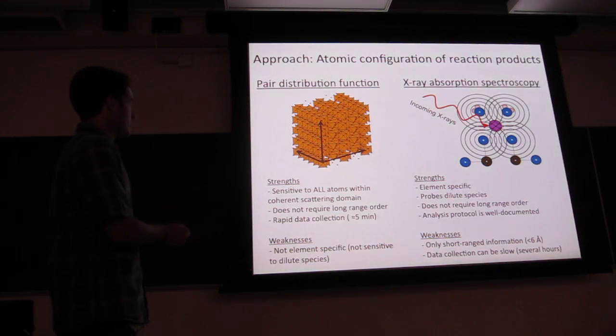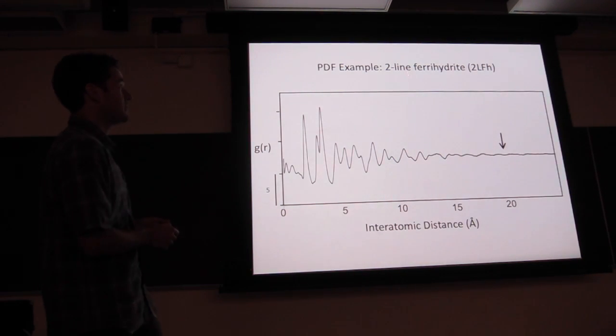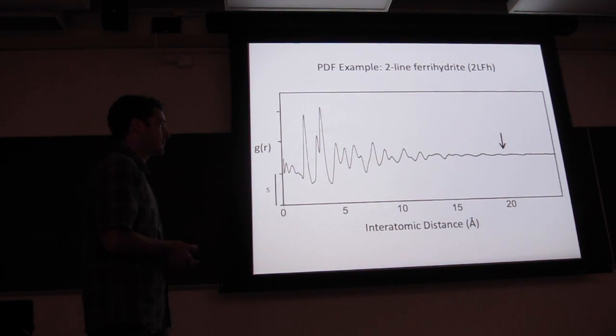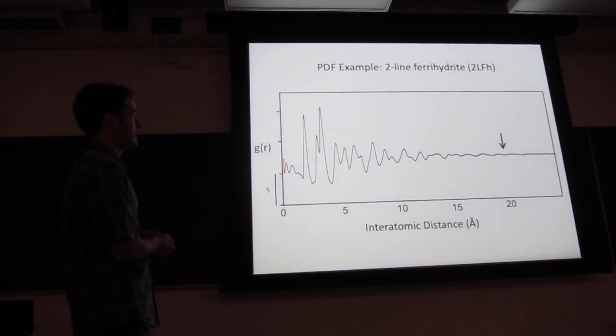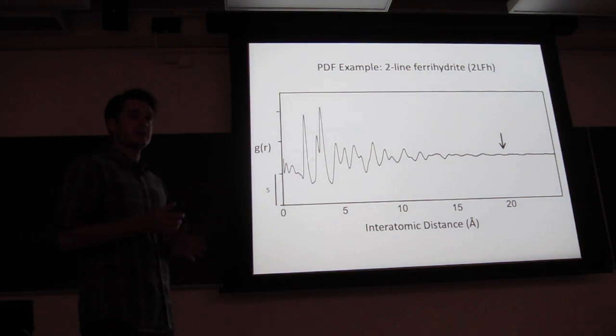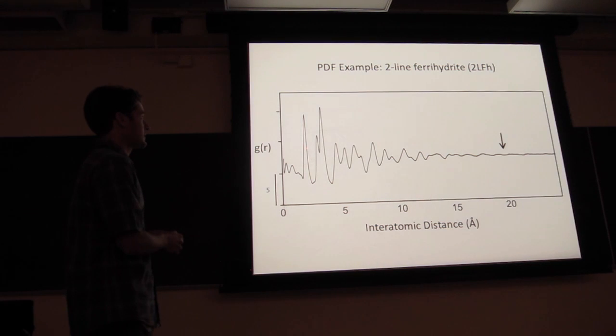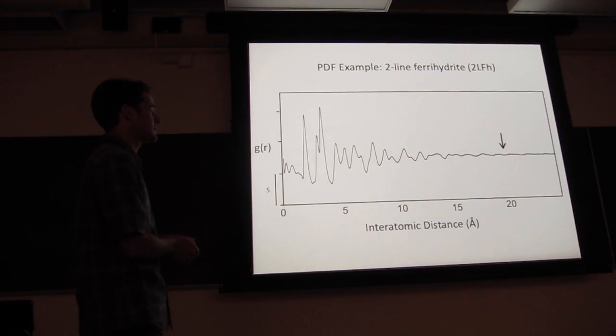All right. So as an example, I'm showing the PDF of 2-line ferrihydrite, which again is that reference mineral that people like to talk about in the literature. And you can see a distribution of peaks that correspond to interatomic distances. And this first peak is iron-oxygen. These two peaks here are iron-iron. And you can actually index all of these peaks.